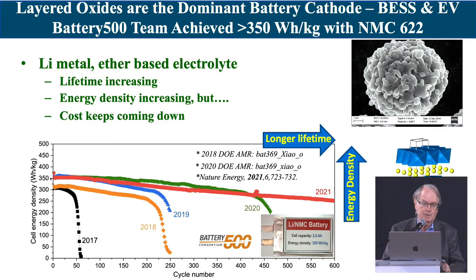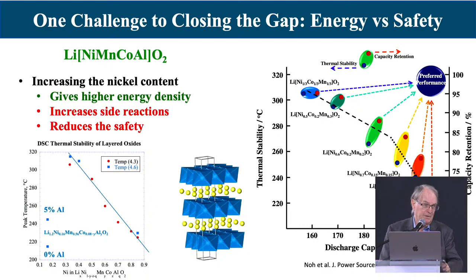But as I said, we want to eliminate as much of the cobalt as we can. We also want to increase the energy density of these cells as far as we can. And the figure on the right shows you the discharge capacity we can get as a function of the nickel content. So the higher the nickel content, the more the energy density you can get. But if you look at the vertical axis now, we show you the thermal stability there. That's the temperature at which these materials, after you take out most of the lithium, will release oxygen. So I said they're metastable. These transition metals don't want to be 4+, so they'll tend to release oxygen.